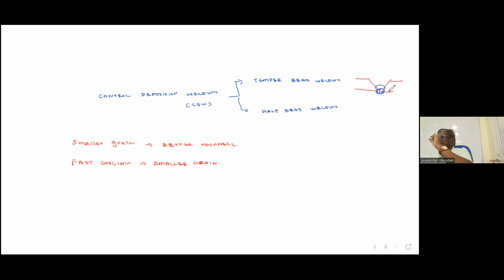The only thing is you have to make a very thin pass so that the entire thickness is heated. Second thing, you have to move it fast. Fast only will result in fast cooling. So when you make small passes like this, every time the grain size of the previous pass is altered. Now to make the final pass, we will weld one more extra pass, then we will grind and remove it. This type of welding is called temper bead welding. What is meant by temper bead welding? Tempering is the heat treatment to improve toughness. By welding, you are altering the grain size of the previous pass.